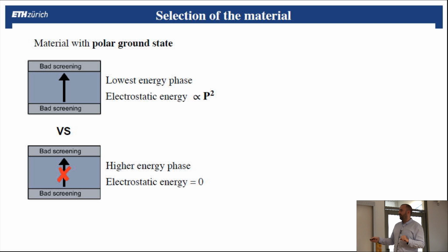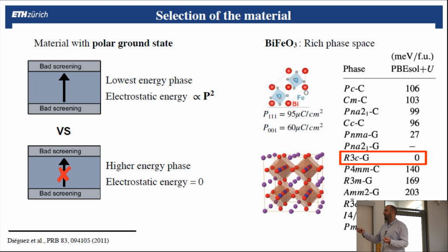In the other case, if we assume that we have now a phase transition to a non-polar phase of the same material, that means that the internal energy would be higher here because it's not the ground state, but there would be no electrostatic energy to pay. So it could be that one can find a balance that would favor this case over this case.